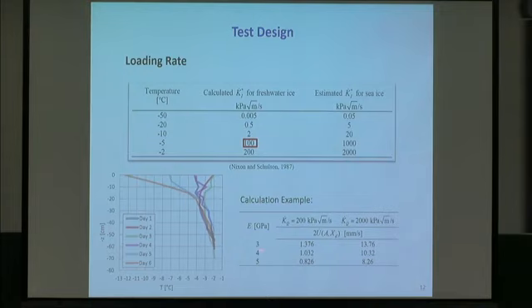When it comes to the loading rate, it's a little bit the same considerations here with the speed of what you should apply, and we went for different ranges here because beforehand we didn't know exactly what we could need, for instance of temperature in the ice and so on. So here is a profile of a typical temperature we had in the ice, which in this case for these tests here were about 60 centimeter thick.